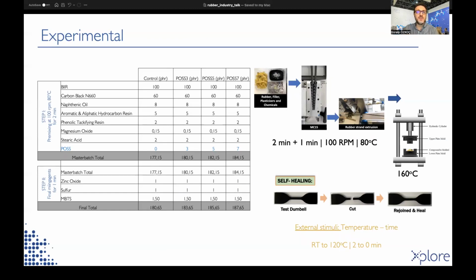After cross-linking, the samples were cured in a hot press, and then the dumbbell-shaped samples were punched from the cured sheets for self-healing tests. In order to investigate the self-healing properties, we cut the dumbbell shape into 2 pieces using scissors, then brought 2 parts together from the wounded part. As a stimulus, we applied temperature ranging from room temperature to 120 C for different application times.